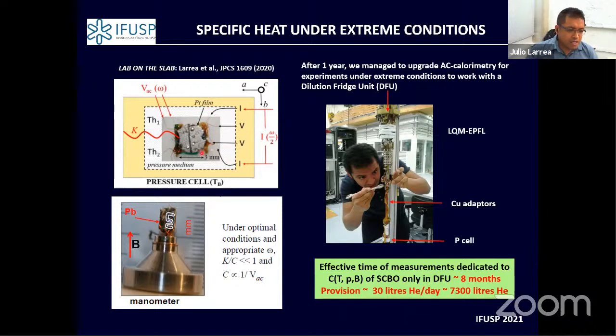In addition, here is just the backside picture of this mount. This is a sample holder for our pressure cell. On this side, I represented a piece of lead that works like a manometer. We measure the superconducting transition and the pressure; our calibration is ex situ. It means every time we change the pressure, we have to remove the cell, warm it up, change the pressure, and put it back again.